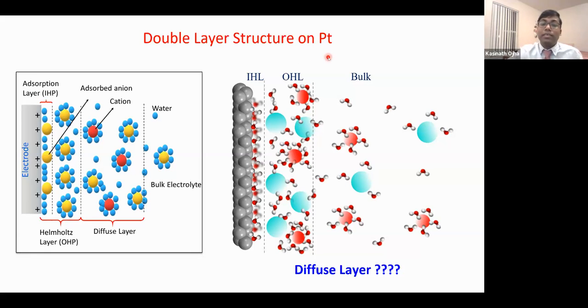So Dr. Kashinath, was this possible because of your lower concentration of electrolyte? No, even at high concentration, all the ions come closer to the surface. Now, how do we understand? Because I did all the experiments at low concentration. At low concentration, the ions should be distributed a bit farther, and we should see the diffuse layer much more prominently than at high concentration. Okay. Dr. Kashi, what was the concentration of electrolyte? I used 100 micromolar.